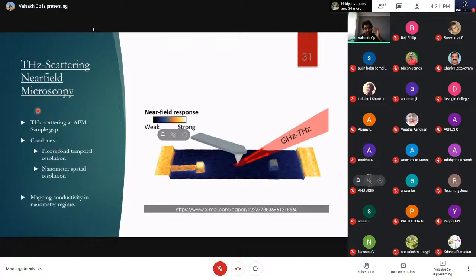So in such experiments, this is an advanced version of terahertz spectroscopy, and we are basically looking at how the radiation scatters at the AFM tips. By doing so the scattering is extremely sensitive to the dielectric environment beneath the AFM tip. And by mapping the scattering of a surface, you could understand the conductivity of the environment directly beneath an AFM tip. And this would help us understand conductivity on the nanometer scale.